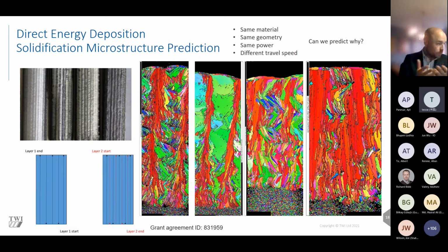And the proof is in the pudding. We can see here a bunch of different walls. These are cross-sectional slices of the walls that were built with Inconel 718. Same material, same geometry, same power, about 2 kilowatts, different travel speeds. And just that change in travel speed was enough to trigger very, very different solidification microstructures. Some exhibit this railroad track down selection of preferential grain orientations. Others have a much more mixed structure.